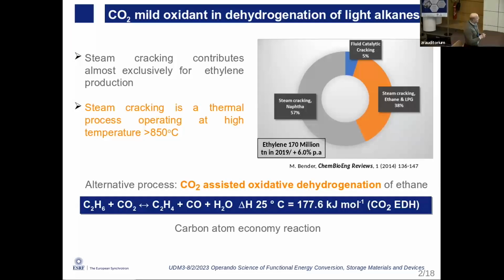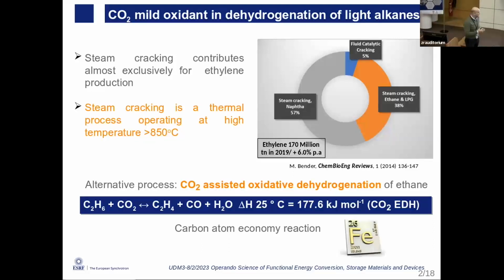And of course, side carbon fission of the carbon can occur. So we need the catalyst to promote selectively the CH fission. And for this aim, typically chromium catalysts are used with a good high conversion rate. However, the problem is chromium is also pollutant. If you want to have a green, environmentally friendly catalyst, the idea is to use atoms like iron. That is good. And the challenge of this research is to try to find the best catalyst to have higher selectivity and also conversion.